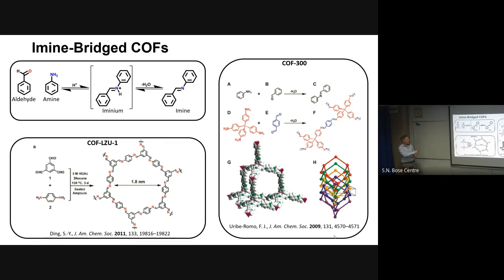So essentially, you are reacting a multitopic aldehyde with an amine, which goes through this iminium transition state. You have to feed in some protons, for example through acetic acid addition, and then you form this imine bond. It's very important that this is a reversible process, because this helps make the framework structures very crystalline, because you can essentially repair defects that form during the reaction process.